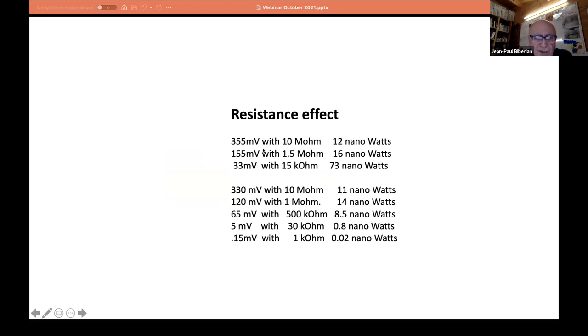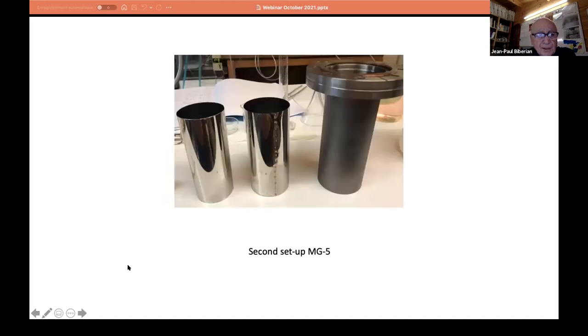You can see here, I've changed the loading resistance. I could measure the voltage and the power because I could measure current and voltage. It's in the nanowatts. I mean, it's not much, a few tens of nanowatts, but it is significant. It's not a measurement error. So next I tried to use another system with larger tubes. Instead of a 2 millimeter tube, I took a wider diameter tube, coaxially to each other, to have more surface area so that the current will increase.